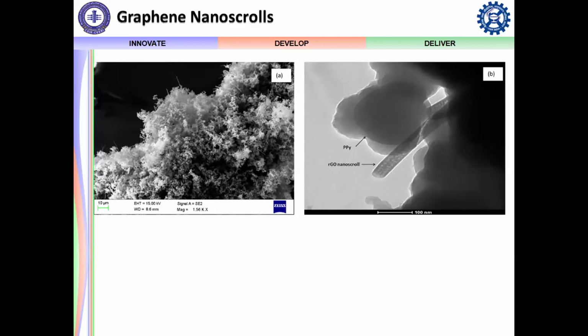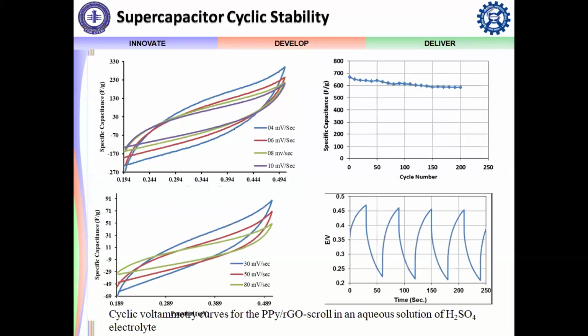and on the left hand side, we can see that it is a very porous structure, and the graphene nanoscrolls are embedded into this polymer matrix. So this material is then used for the supercapacitor. And then we have done the cyclic stability test of these materials. The good part of this material is that it can be fabricated directly on the microstructures if we dip it in the solution, followed by the electrolyte encapsulation.